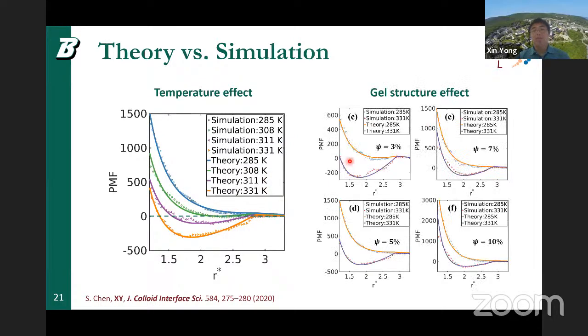We also looked at what happens if we vary the cross-linker density of the gel. So here we explore different densities. As we gradually increase the cross-linker density of the microgel, the microgel becomes more rigid, and so the elastic contribution starts to become more dominant. This can be evidenced from the difference between the two temperature curves getting smaller and smaller, as you can see here. The gap, and the attraction well, get shallower as the cross-linker density increases.